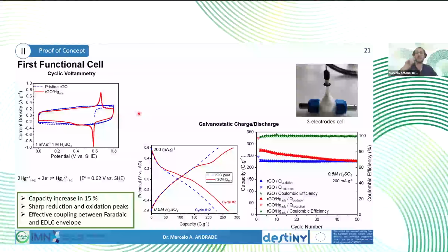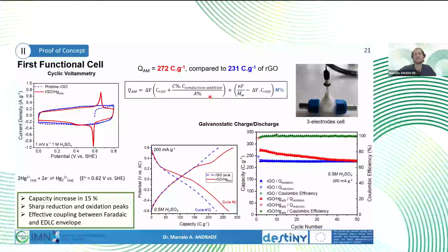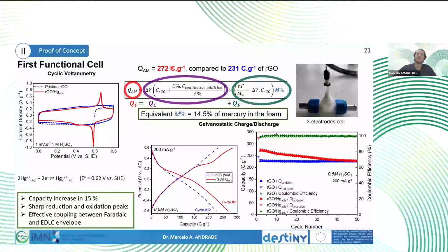So it is important to notice that RGO is already a material that is used in both worlds, so adsorption and energy storage. So it's already used and explored as energy storage material for high power application for supercapacitor. But once used as an adsorbent before, it increases its capacity by the heavy metals that it has entrapped. So if we calculate back how much capacity we get from the mercury containing RGO, we can calculate what mass of mercury it would correspond to, and it gives 14.5 percent in the total foam, given that we found 16 by EDX. So that also can correlate to the capacity that we obtain from the heavy metal.